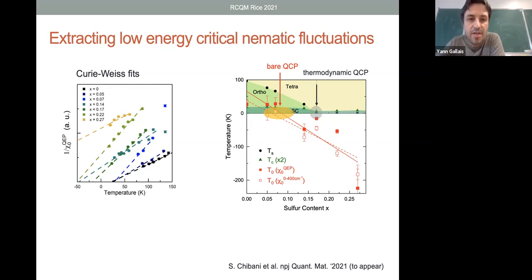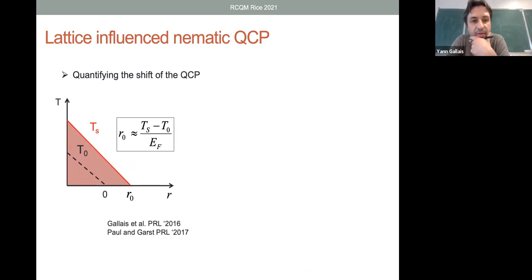Of course, sulfur doping is not really a correct way of comparing things because it's a bit arbitrary. So one would like to have some kind of dimensionless parameter to quantify this lattice shift. One way to do that is to use T_S minus T_nematic as a nematic energy scale and renormalize it to an energy scale of the electrons, which in our case would be the Fermi energy. Then the phase diagram would be T versus this dimensionless parameter, and the shift R_0 would be precisely this parameter. That's a way to quantify the shift, and this shift has to happen because it's an unavoidable consequence of the fact that T_S and T_nematic are different, and therefore their associated QCPs have to be different.